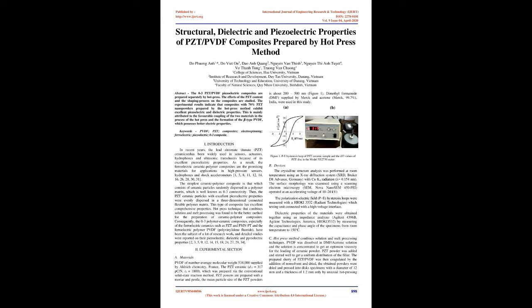The PZT ceramic, D33 equals 317 pC/N, relative permittivity equals 1800, which was prepared via the conventional solid-state reaction method. PZT powders are prepared with a mortar and pestle. The mean particle size of the PZT powders is about 200-500 nm, Figure 1.